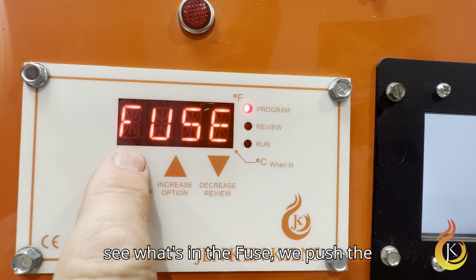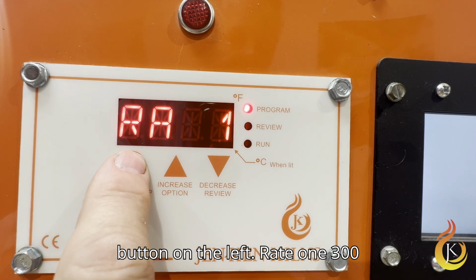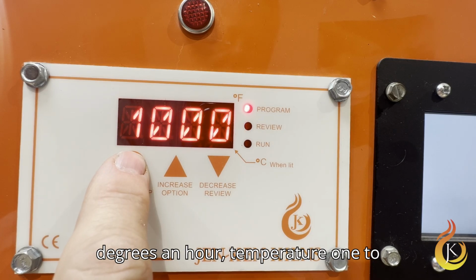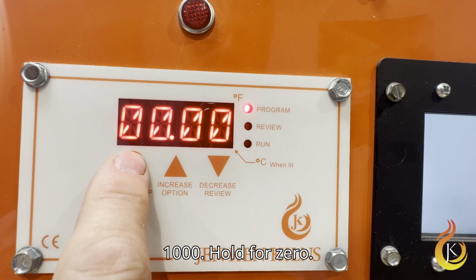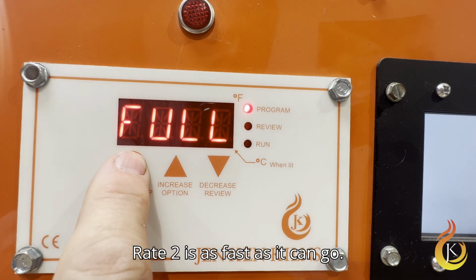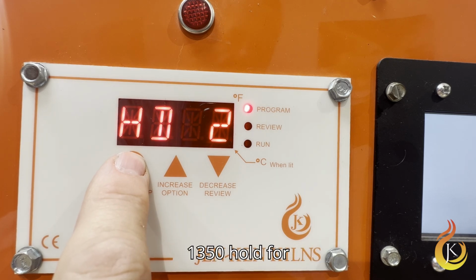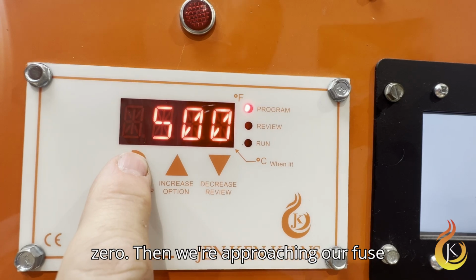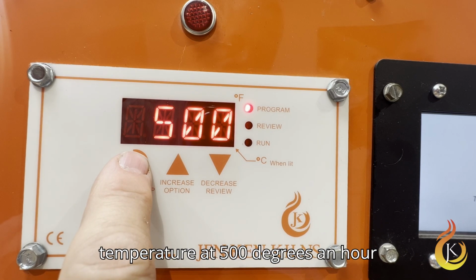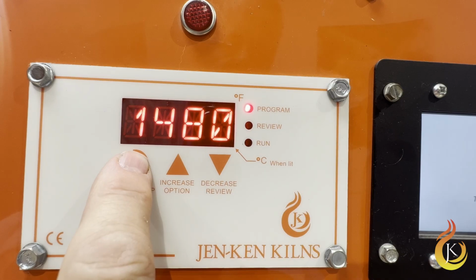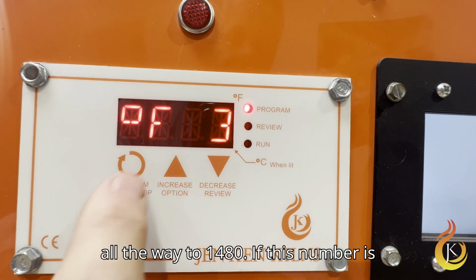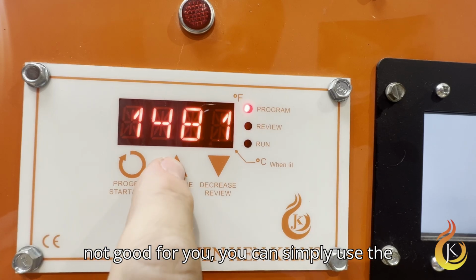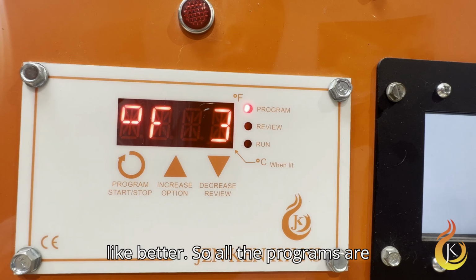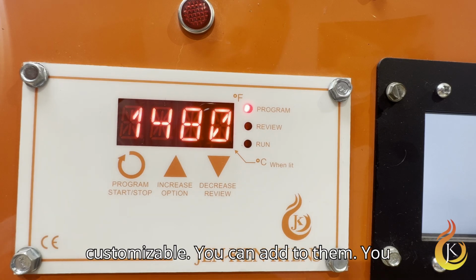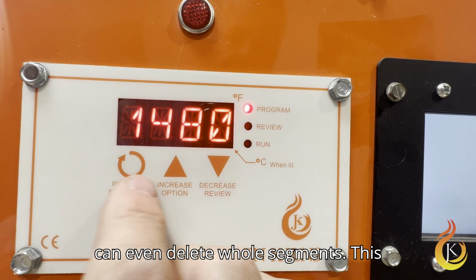If we want to see what's in the fuse, we push the button on the left. Rate 1, 300 degrees an hour. Temperature 1 to 1,000. Hold for 0. Rate 2 is as fast as it can go. 1350. Hold for 0. Then we're approaching our fuse temperature at 500 degrees an hour, all the way to 1480. If this number is not good for you, you can simply use the arrows and change it to a number that you like better. So all the programs are customizable. You can add to them.